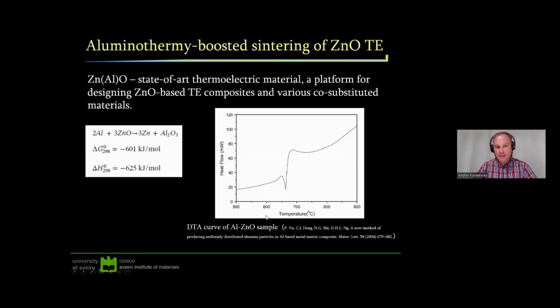If you look at the DTA curve, you can see that the reaction starts at temperatures around 660, the melting point of aluminum, and is associated with evolution of a significant amount of heat. So what will happen is that in some places of our sample we will have local overheating, and this local overheating could be very interesting for different purposes.